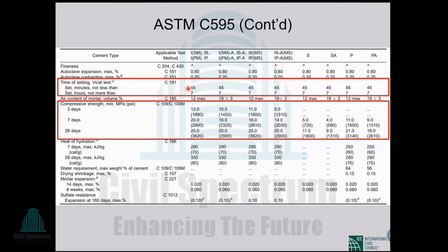initial setting time must be, oh sorry, this one is more liberal, EN is more strict. The initial setting time for 42.5 strength class is 60 minutes. So initial setting time must be more than 60 minutes in case of EN. But in case of ASTM, if it is more than 45 minutes, then it's okay. The problem was the final setting time. Final setting time must be less than 7 hours, which is 420 minutes.